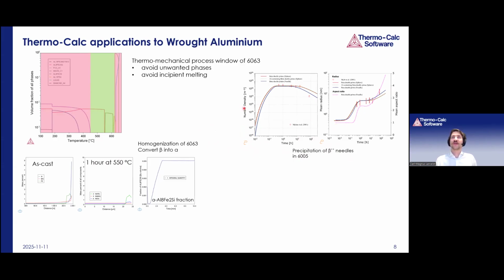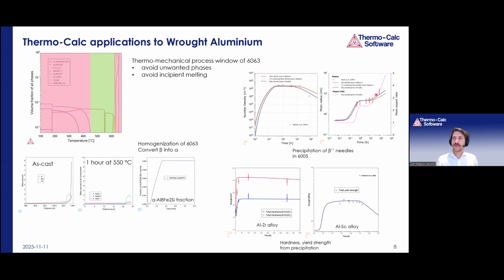So here we look at the number density of the particles as a function of time during the precipitation treatment, and also the mean radius and the aspect ratio of the particle as a function of time. And then when you've done this kind of simulation and you're happy with the results, you can use this to model the hardening of the material.